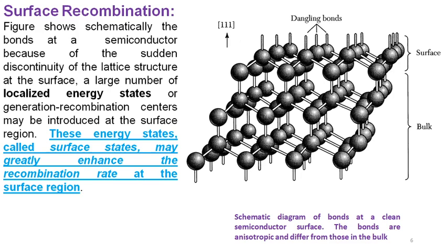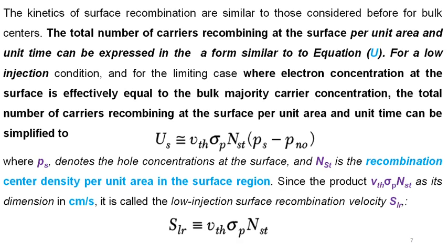That's why dangling bonds in the material play a very important role in reducing the optical properties of the material. So for those applications where the photoluminescence properties of the material are very important, the material should not contain dangling bonds or unsatisfied bonds, because they can enhance electron-hole recombination, and it will affect the optical properties of the material, as shown in the figure here.